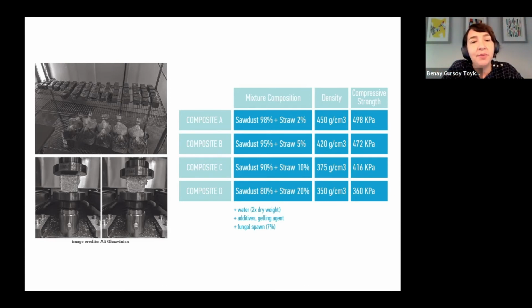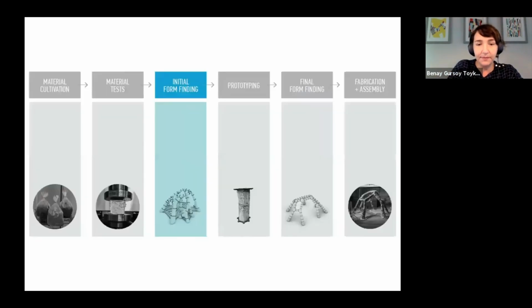Then, comparing all these samples under compressive strength tests, we identified 4 composite mixtures that performed the best in terms of compressive strength. And then we decided to use these 4 different composites in different parts of the structure, depending on where we need heavier and stronger materials, and towards the upper parts of the structure we would need lighter materials.